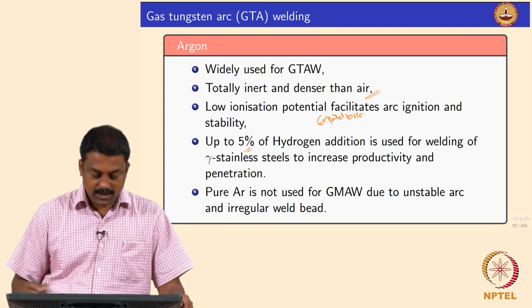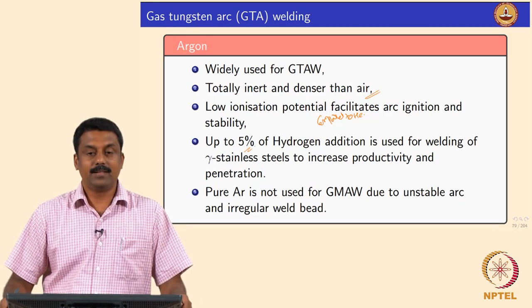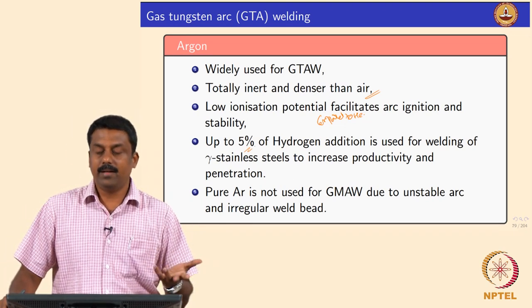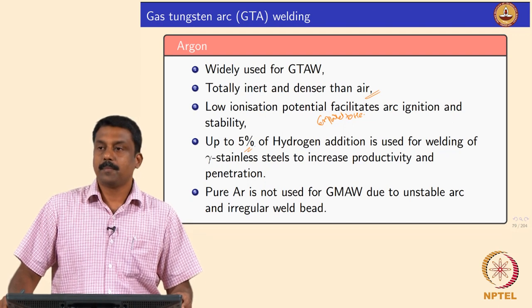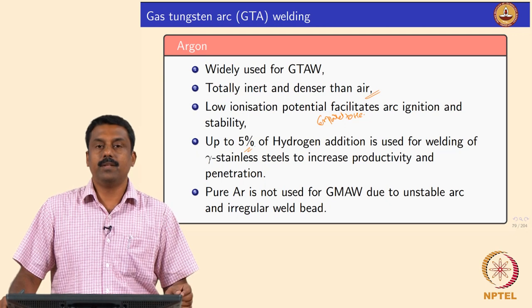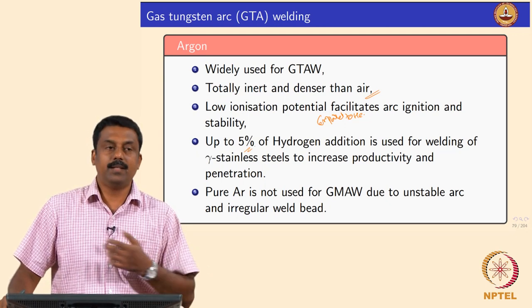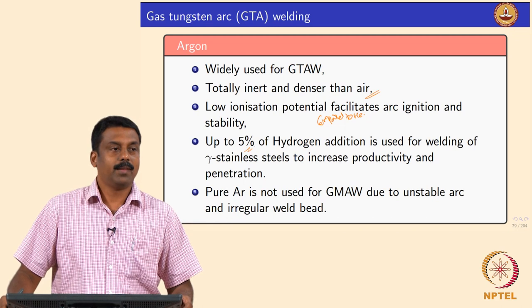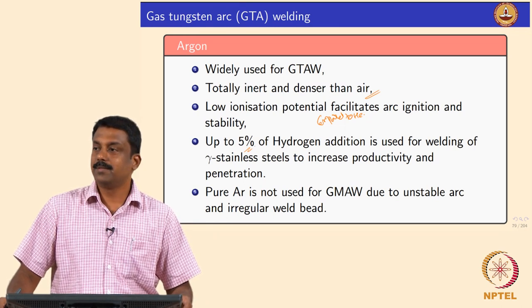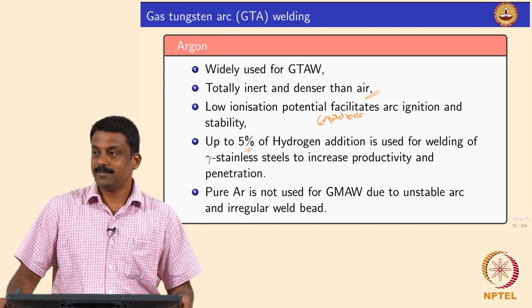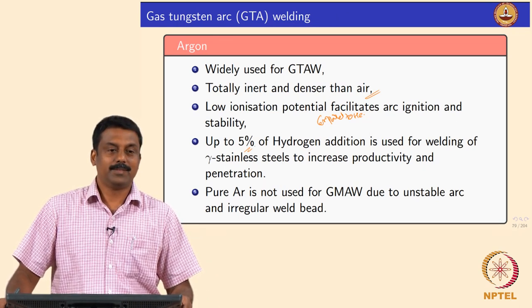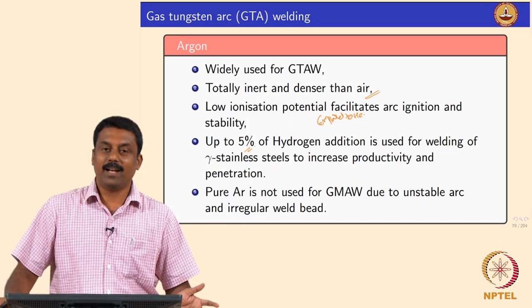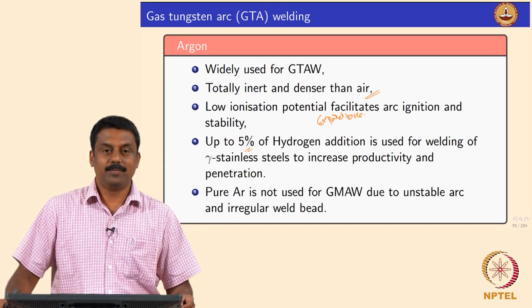Sometimes we add about 5% hydrogen so that the heat is distributed and you make a wider bead. However, you cannot use hydrogen mixing for low-carbon steels or ferritic steels — if you use hydrogen for welding low-carbon steel, the weld will crack by hydrogen embrittlement. Pure argon is generally not used for GMAW because heat concentrates highly at the arc core and the melting characteristics of the filler cannot be ensured properly; the transfer characteristics are significantly affected by the shape of the arc core.